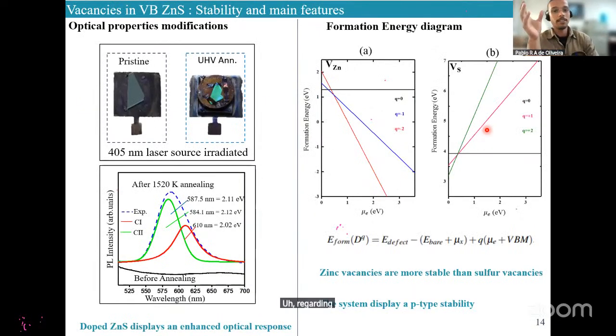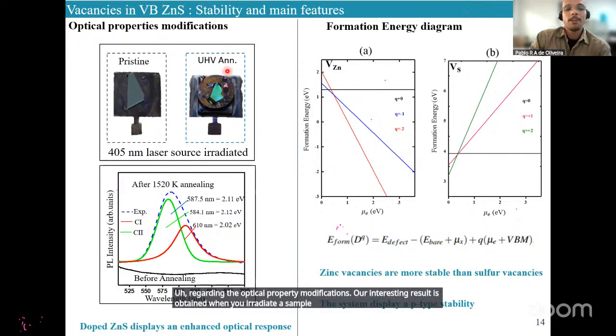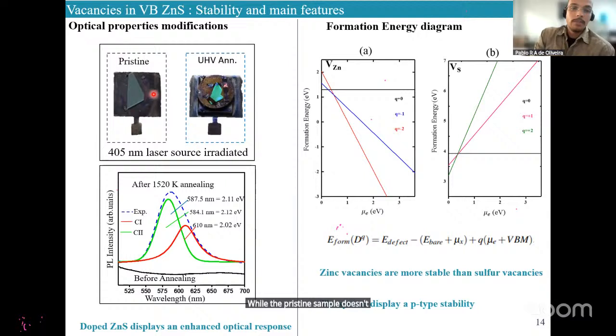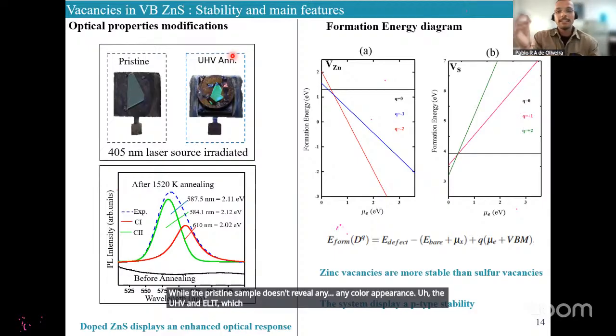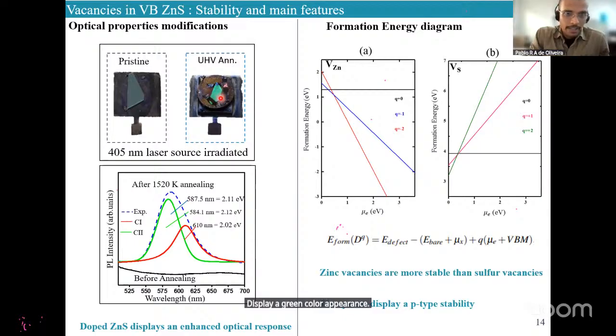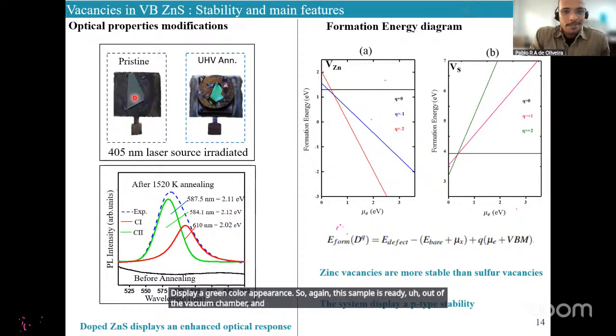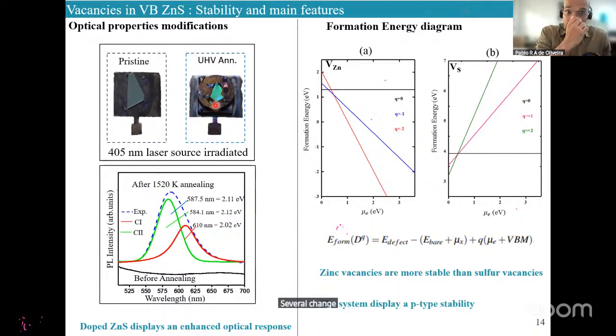Regarding the optical property modifications, an interesting result is obtained when you irradiate a sample with 405 nanometers. While the pristine sample doesn't reveal any color appearance, the UHV annealed, which means the defective sample, displays a green color appearance. So again, the sample is irradiated out of the vacuum chamber, and this subtle change is noticeable to us by the naked eye.